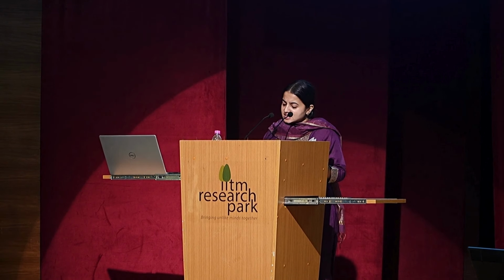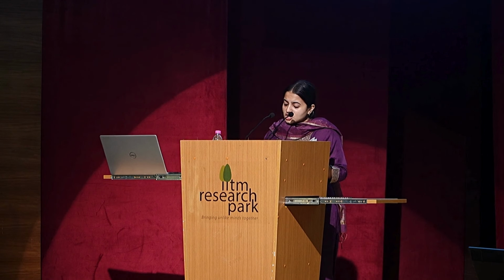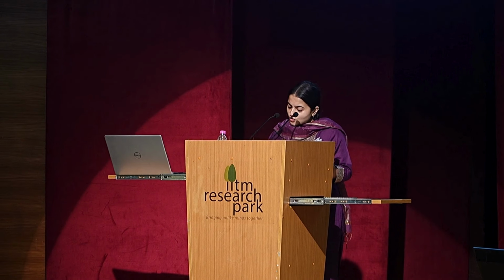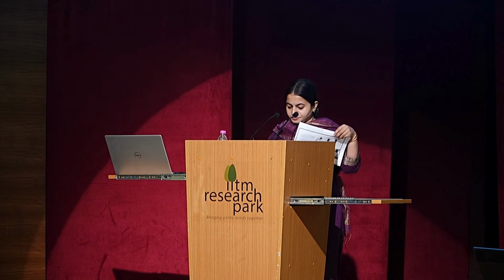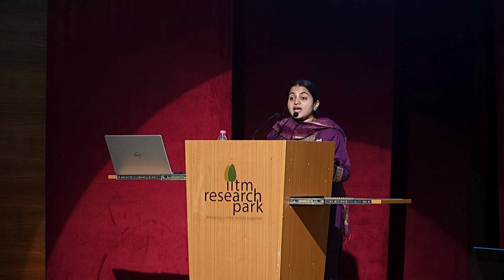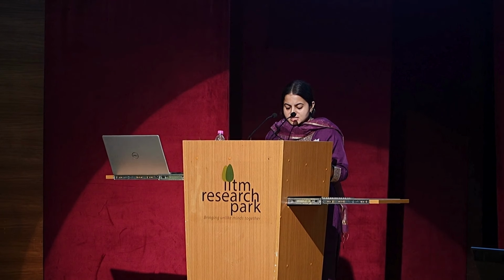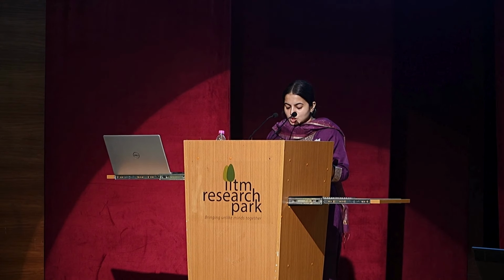Ministry of Steel has released a green steel taxonomy where star ratings are based on the level of CO2 per ton of finished steel, where 3-star is between 2 to 2.2 ton, 4-star is between 1.6 to 2, and 5-star is less than 1.6. ARS is #1 in the country to receive the green steel certificate from the Ministry of Steel. ARS leads the nation as the #1 producer of low CO2 TMT bars with 5-star rating. ARS Steels is around 2.5 times better than the best with CO2 emission intensity of 0.6432 ton CO2 per ton of finished steel.